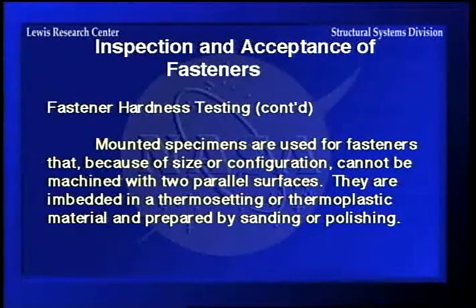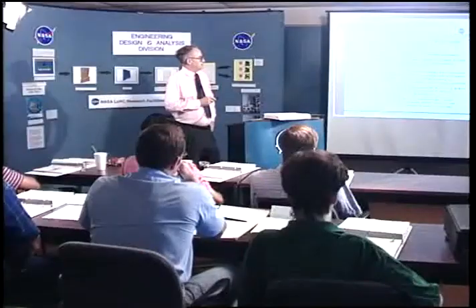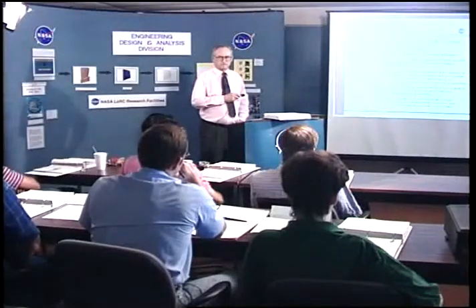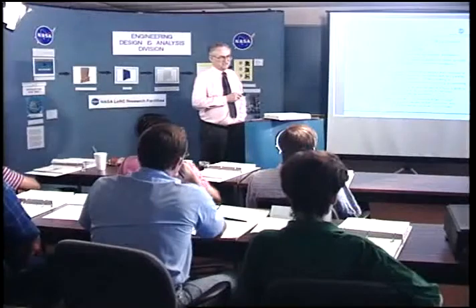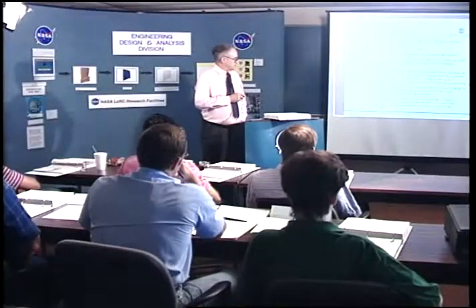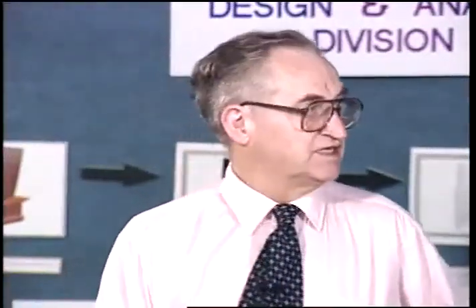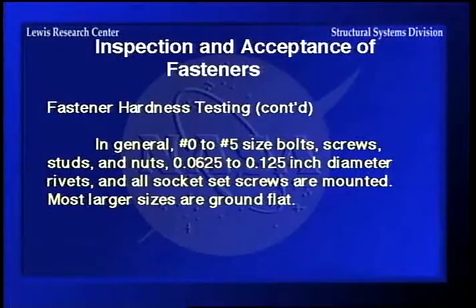The other thing you can do, if you have small fasteners that you can't do that with, is mount them, and these metallurgical people can put them in a nice little thermoplastic type setting that you can then put on the platform and get hardness testing. And the beauty of that is, since you can't get through hardening in a fastener in a lot of materials above about 3/4 inch diameter, you need to take hardness readings both close to the threads and at the core to see whether you're getting the true strength indication for the fastener. So on the little ones, this is a 0 to number 5, so that's 60 thousandths to an 1/8 diameter.